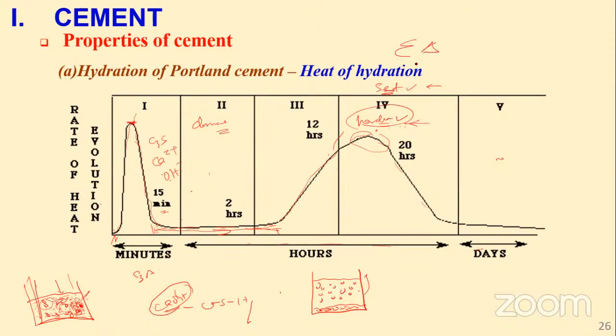Remember, the total heat is the summation of the heat of the four compounds, for i equals one all the way to four, where one to four are these ingredients: tricalcium silicate, dicalcium silicate, tricalcium aluminate, and tetracalcium aluminoferrite. And each of these generates the hydrated compound plus heat. So depending on the rate at which heat is released, if we have a high composition of tricalcium silicate and tricalcium aluminate, which react at earlier stages, then the heat of hydration will be higher.